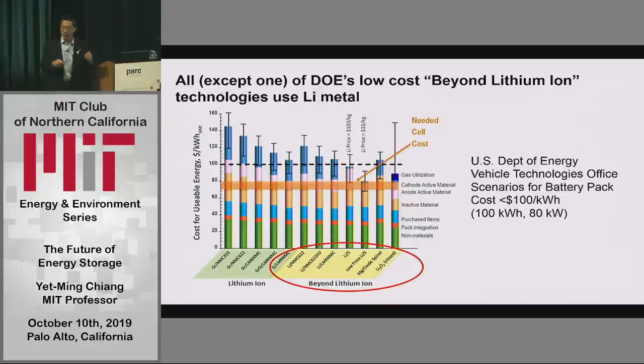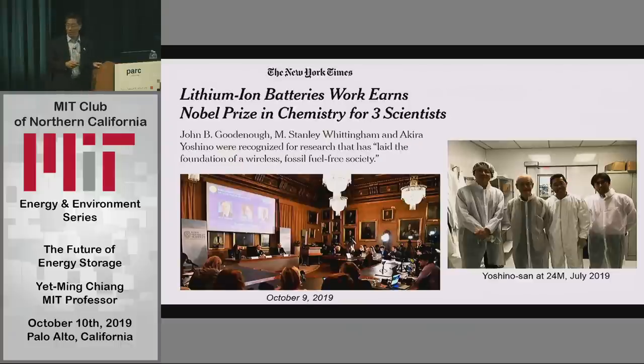And so the reason that using lithium metal is so important from the energy density point of view is that you can't do any better than having your working ion precipitate and form a solid when it comes to the electrode. You get rid of all the hosts that otherwise have to store that lithium ion. And so those are the ones that we focus on. And not only for energy density, this is actually a cost plot because the vertical axis is cost. And getting below a bar here of $100 per kilowatt hour is a longstanding goal of the DOE. So they see that these are the chemistries that can do it. Some of you saw this just yesterday.